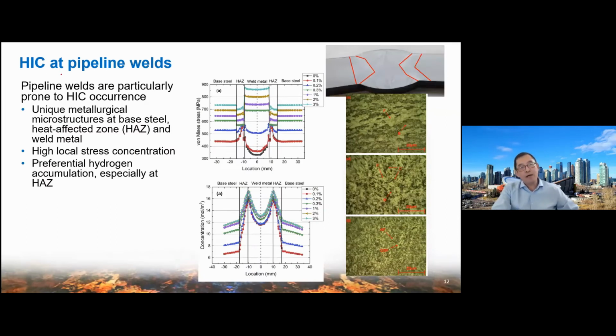When we talk about hydrogen-induced cracking of metals such as pipeline steel, please don't forget the pipeline is welded infrastructure. So hydrogen-induced cracking in the welding area is particularly important. There are 3 reasons. First one, the pipeline welding area has a unique metallurgical microstructure. You can see from the metallographic picture on the right side, the base steel, the heat affected zone HAZ, and the weld metal have different microstructures. Particularly in the middle one, HAZ, in addition to F, ferrite, and B, bainite, it also has C, cementite. This is a hard and brittle phase, which can make hydrogen-induced cracking more sensitive.